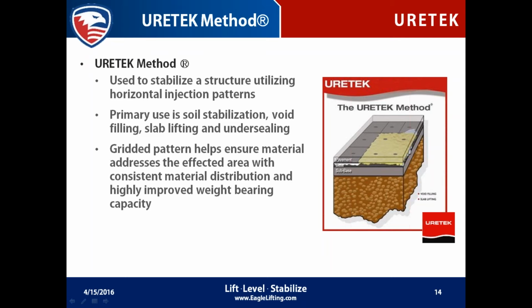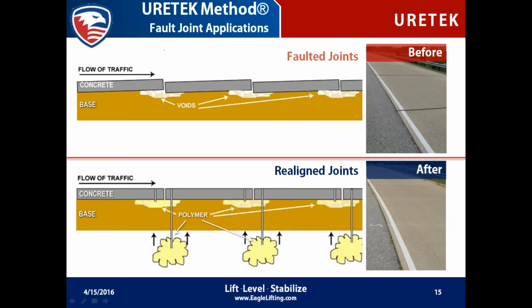The gridded patterns help to ensure the material addresses the affected area, and it's consistent with material distribution and highly improved weight-bearing capacity. What we mean there is if you have a section of roadway or rocking slabs inside a warehouse, where every time a forklift drives over it, it rocks and begins to crack and fail, by restoring the connection of the soil to the underside of that slab, the load distribution is more even across that slab, which improves the weight-bearing capacity of the slab throughout. So once again, we are buying more life out of the infrastructure that exists, and once again, it's without excavation.